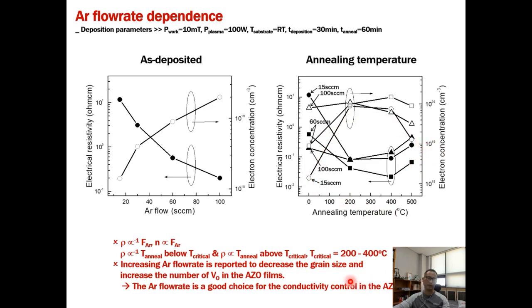We can say that increasing argon flow rate is reported to decrease grain size and increase the number of oxygen vacancies in the AZO thin films. The argon flow rate is a good choice for the conductivity control in the AZO film.